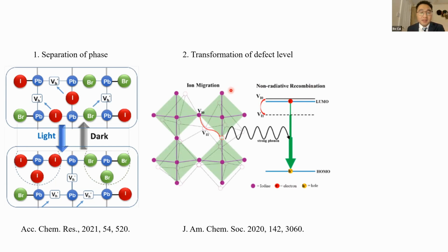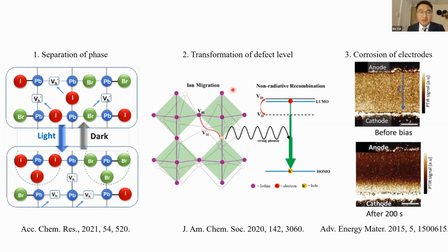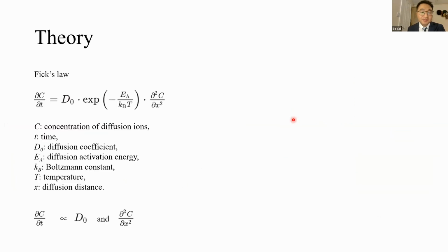Last, long-term migration would induce accumulation of halide atoms near the electrodes and promote the reaction between halide atoms and metal electrodes, inducing the corrosion of electrodes. So we should and we must solve the problem.